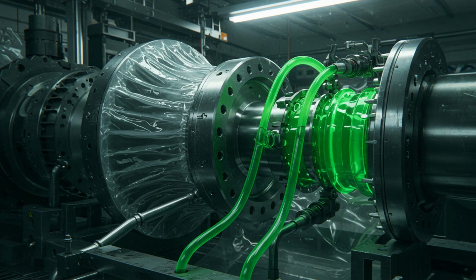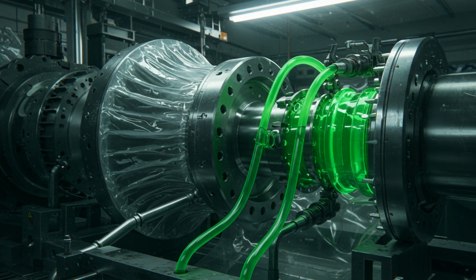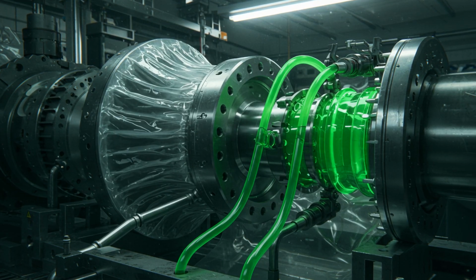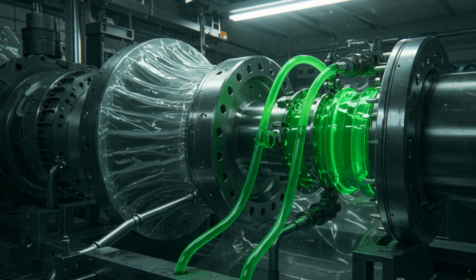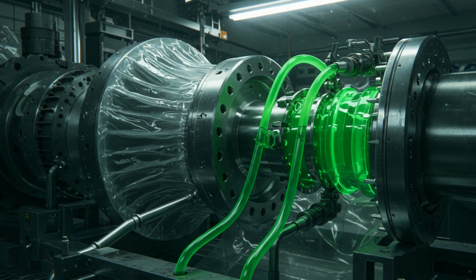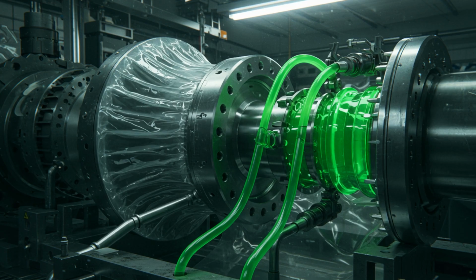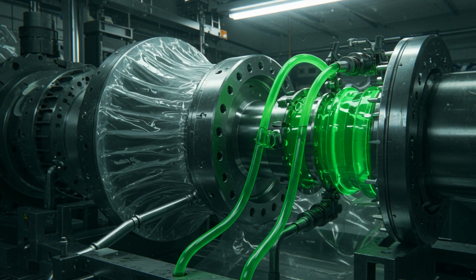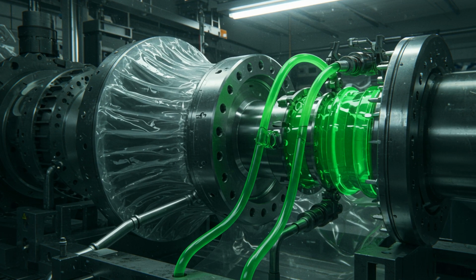Once the dry fibers and balsa core are perfectly positioned, the entire mold is sealed under a massive plastic vacuum bag. This is the moment of truth, the resin infusion. Using powerful vacuum pumps, all the air is sucked out from the mold, creating a powerful negative pressure. Then, valves are opened, allowing liquid epoxy resin to be pulled into the vacuum. This isn't just pouring, it is a controlled chemical flood. The resin must penetrate every single layer of fiber, saturating the glass and carbon to create a solid, monolithic structure.